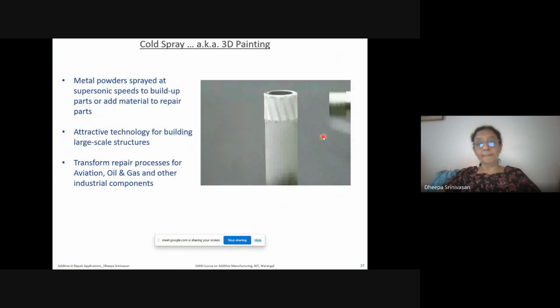Okay, so the last example is that of cold spray, because cold spray is basically not a melting and solidification process. Here, what happens is you have a nozzle, which is a convergent divergent nozzle, using process gas such as very low atomic number and weight gases like helium and nitrogen. The gases carry these powder particles, similar in size range to that of the laser powder bed fusion process, which is between 5 to about 30 to 40 micrometers. And it creates a sort of a Venturi effect, and the gas carries the particles with momentum and smashes them onto the substrate that it is going to have an effect on.